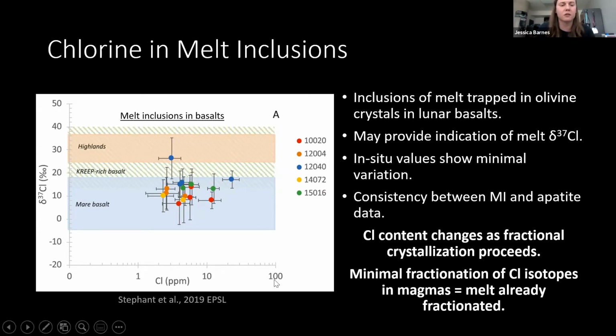They find lower chlorine concentrations, but generally speaking, for the mare basalts, they saw mostly the same range in chlorine isotope compositions that we were seeing in the apatite grains. And this shows that chlorine content changes as fractional crystallization proceeds. So we have a lot lower abundances of chlorine in the melt inclusions, the very pockets of the very first melt to form. But then we have much more chlorine in the residual apatites at the end. But there appears to be minimal fractionation of chlorine isotopes within the magmas themselves, although there are some samples that do show evidence for having degassed chlorine on their way to the surface or at the surface. So Alice's work plus our work showed that the melt had to have already been fractionated with its chlorine isotopes before these rocks formed.